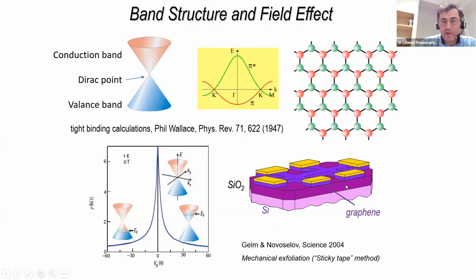However, if we apply a positive gate voltage, we put more electrons, because it sort of works like a capacitor, so we put more electrons in graphene, we start to fill the conduction band with electrons, and these electrons help the material to conduct. So the resistance, as you can see on this plot, is dropping. The resistance as a function of gate voltage is decreasing with increased positive gate voltage. Similar behavior is observed with negative gate voltage. The only difference is that now we are not adding electrons, we're actually taking electrons from the valence band. So we are leaving some empty spaces, and these empty spaces actually behave as electrons with a positive charge. So we call them holes. And it's quite common in semiconductors to have either electronic conductance or hole conductance. So this is nothing unusual.